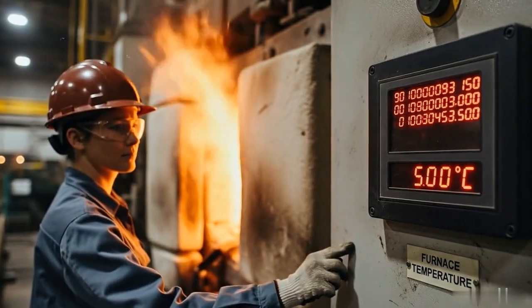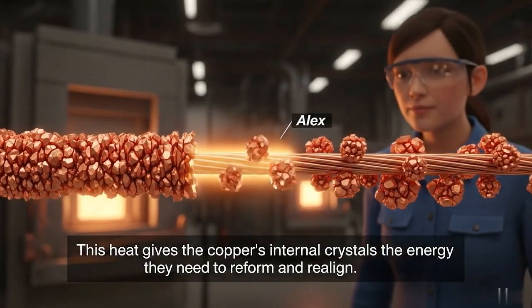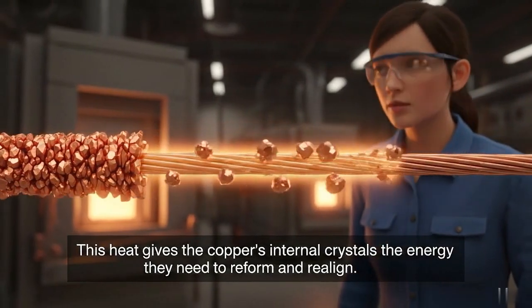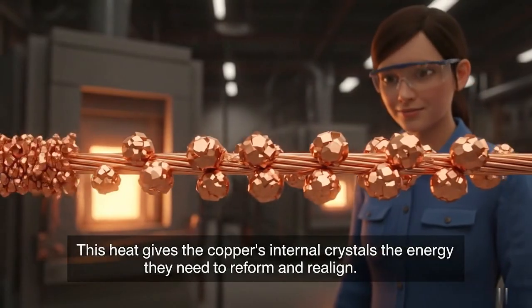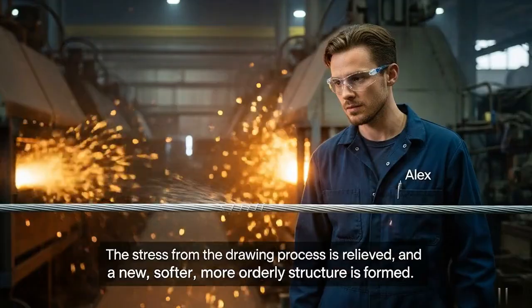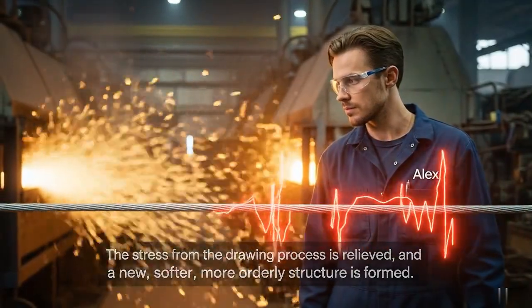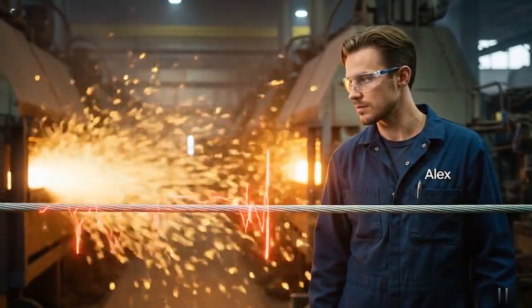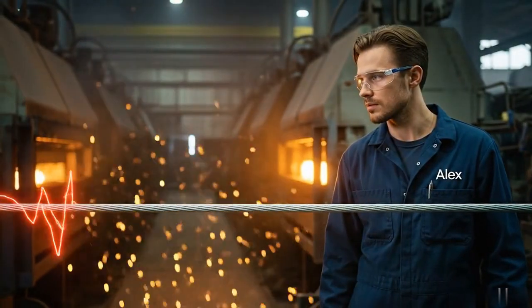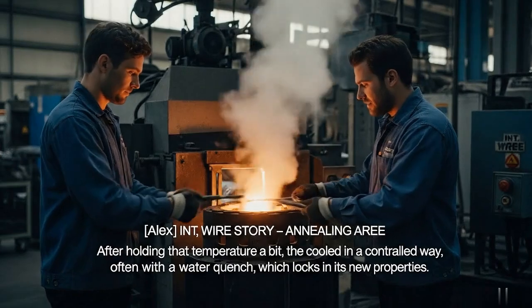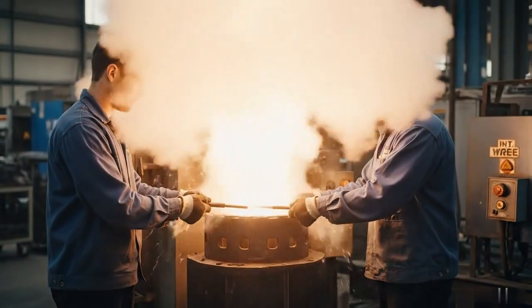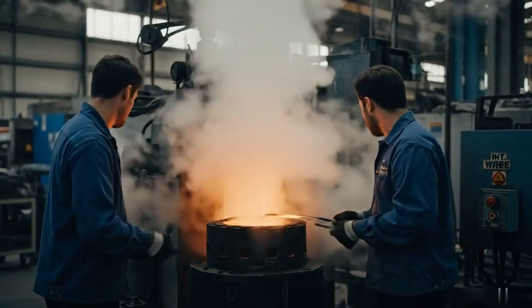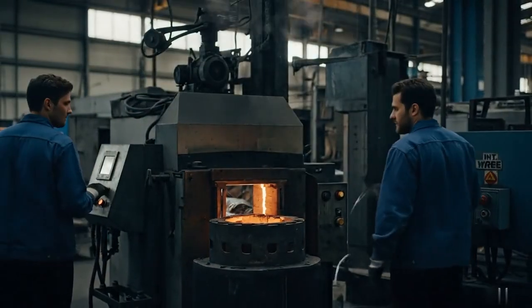The furnace then heats the wire to a specific temperature, usually between 350 and 600 degrees Celsius. This heat gives the copper's internal crystals the energy they need to reform and realign. The stress from the drawing process is relieved, and a new, softer, more orderly structure is formed. After holding that temperature for a bit, the wire is cooled in a controlled way, often with a water quench, which locks in its new properties.